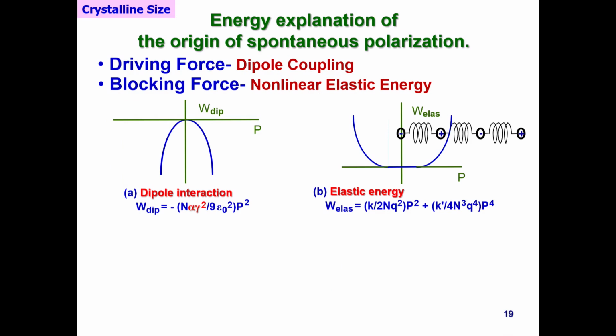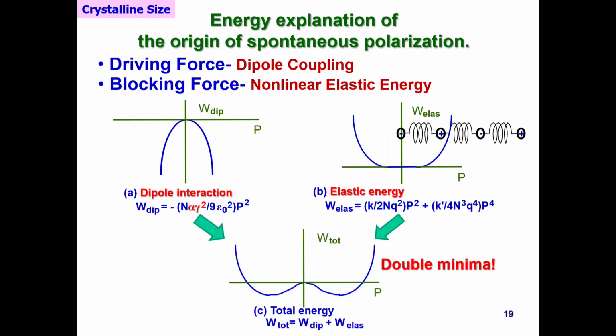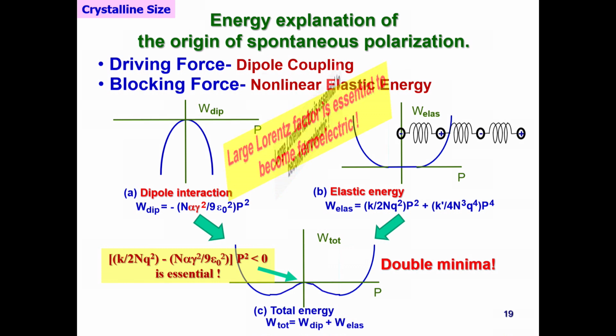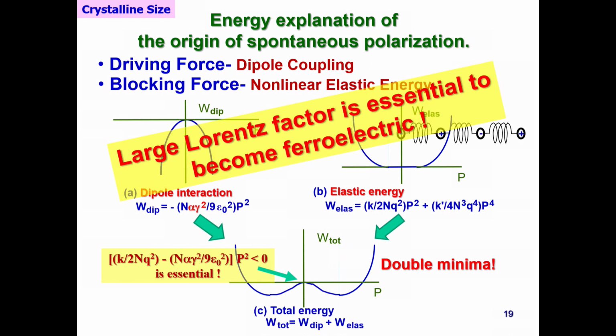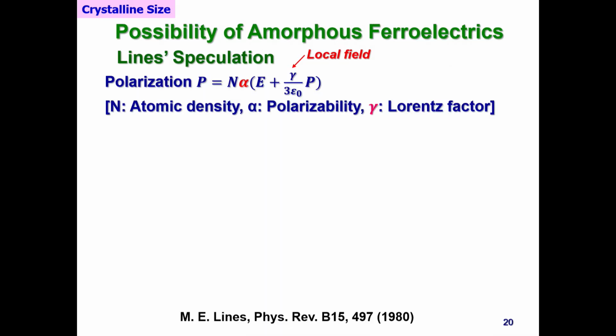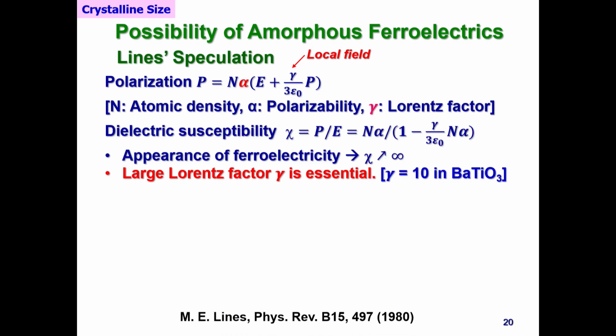If we have a particular polarizability alpha, gamma square, this is the dipole interaction, which tries to separate the cation and anion. And this is the sustained elastic energies. And you can make a double minimum, okay? This is the typical explanation to show the ferroelectricity. So large Lorentz factor is essential to become a ferroelectric. So already in the 1980s, Dr. Lines explained the possibility of amorphous ferroelectrics. So polarization is a polarizability multiplied by local field. And in a short word, large gamma is required.